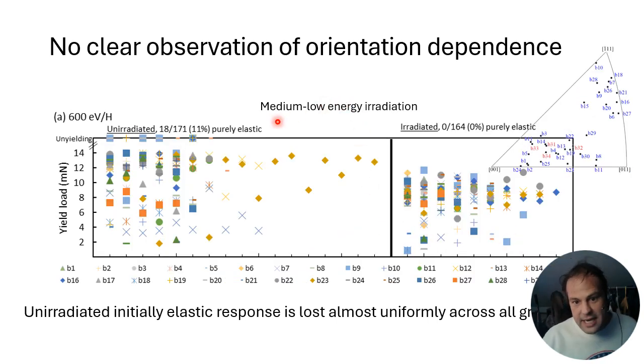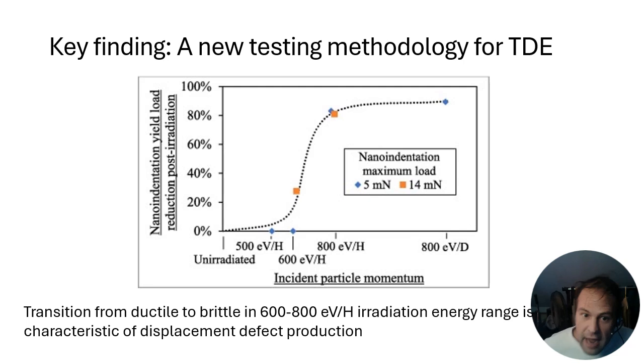Then in a medium low energy condition, the 600 electron volts per hydrogen, we see a little bit of this yield load degradation, but not as much as in the 800 electron volt case. So while we haven't seen this observation of orientation dependence, what we have found is that nanoindentation is a possibly useful new testing methodology for threshold displacement energy.